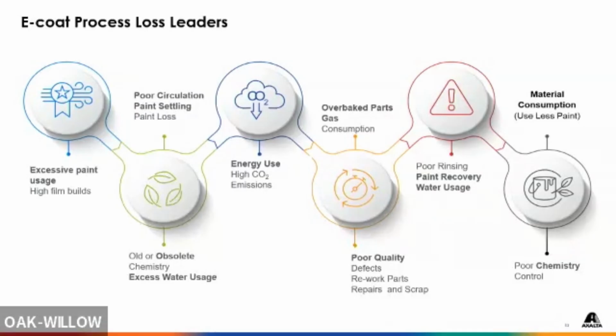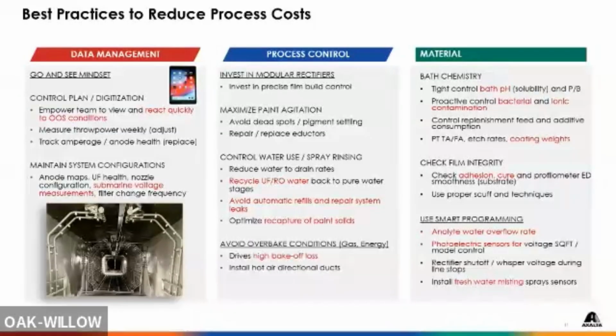And then, again, the set it and forget it mentality. I have a lot of customers that are still stuck in some of their older technologies where they're still putting 25 and 30 microns on these parts. We've demonstrated you can get down to 12 or 13 microns and still protect that part quite well. So that's another reason. And I've worked with some of our end users in this room, and in one particular case we were able to get them about $500,000 in cost savings just by optimizing their process.